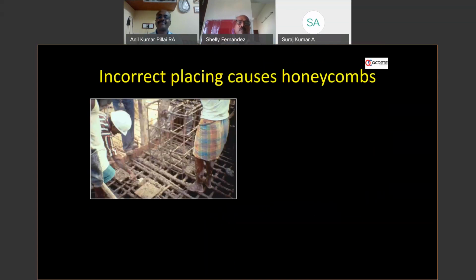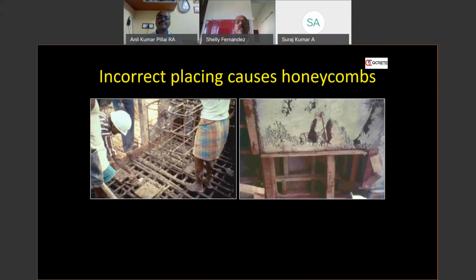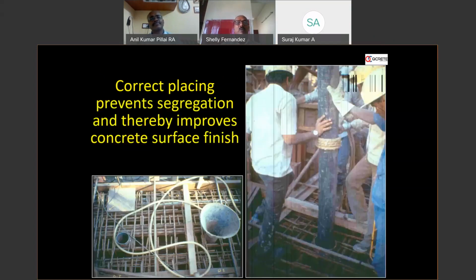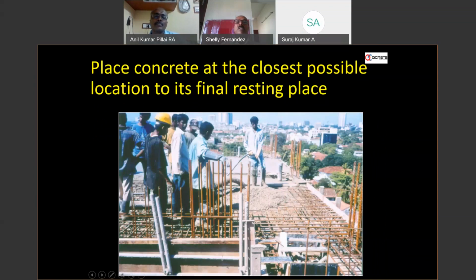Incorrect placing leads to honeycombs. So correct placing also plays a very important role. If you place it properly, as we saw earlier with the tremie pipe for deep foundations with a funnel, the chute or trunk gets attached to the funnel, and the concrete goes below without much hitting onto the steel reinforcement. Without segregation, it is a good concrete. A cohesive concrete is placed at the required location. So placing concrete as close as possible to its final resting place is more important.